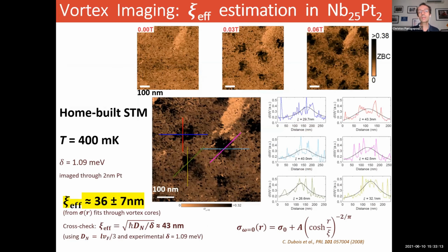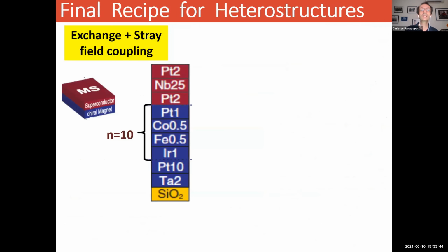And to do that, we have used a home-built scanning tunneling microscope. We measure down to 400 millikelvin, and as you can see here, these are typical images of the superconducting vortices in our niobium platinum. And we can actually measure from here the effective superconducting coherence length in our niobium film capped with platinum. It turns out to be approximately 36 nanometers, indeed a little bit higher than the pure niobium. So now we can have the final recipe for our heterostructure.